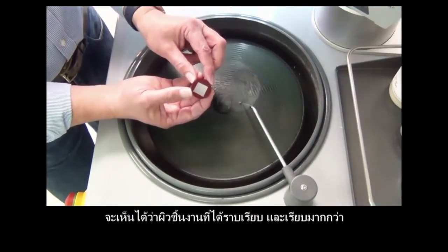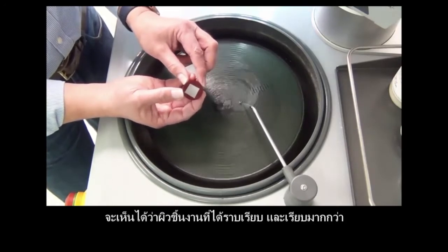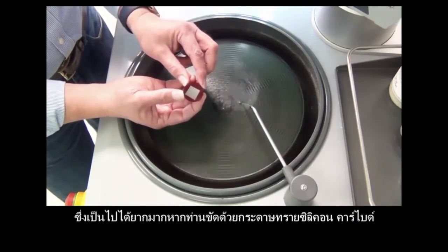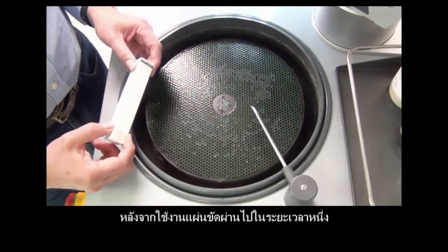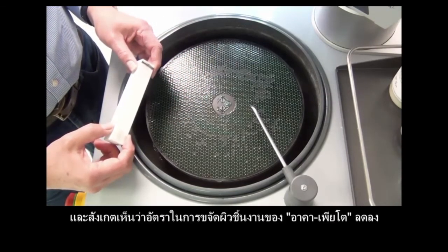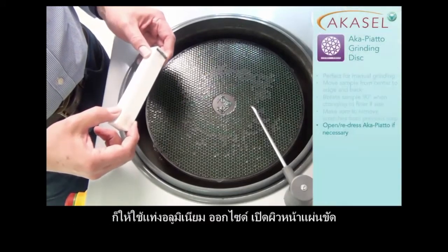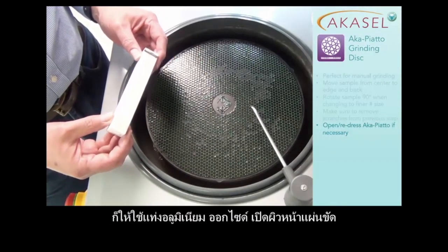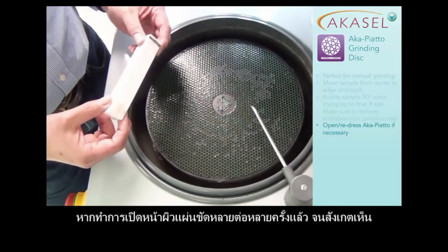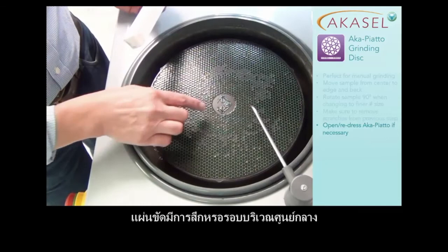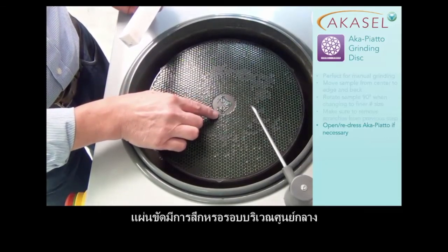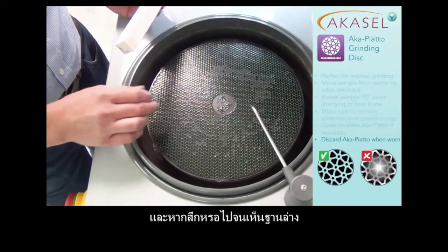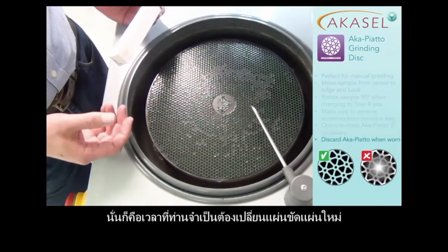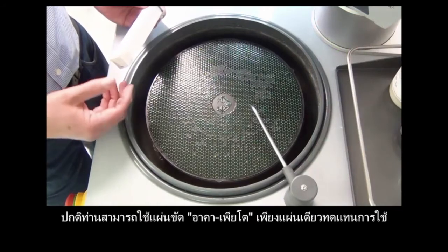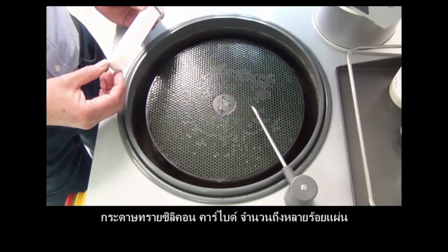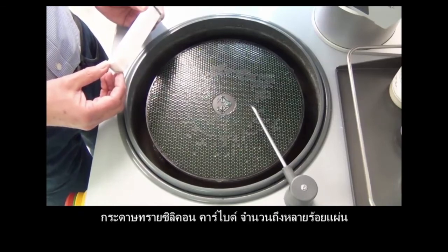Looking at the sample, you can see it is perfectly flat, much more flat than you ever can get it by using silicon carbide paper. If, after some time of grinding, the removal rate on the Aka-Piatto decreases, you can simply open it up, press it again using the aluminum oxide pressing stick. After pressing it several times, you may be seeing that the disc is getting worn mostly at the center, and if the disc is worn down all the way to the base metal, it's time to replace it. But usually you can grind what equals to several packs of silicon carbide paper with one Aka-Piatto.